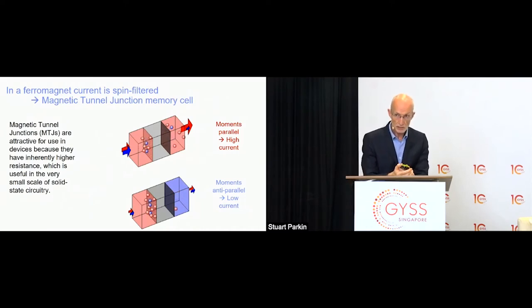Now, when you extract current from the surface of a ferromagnet into an insulator, it turns out, because the material is magnetic, this means there are more electrons with their spins oriented in one direction than the opposing direction. This means automatically the current is spin polarized. Moreover, by choosing that insulating layer properly, the insulating layer itself, even though it's non-magnetic, can further spin filter the current, so that the current, which is tunneling across the insulating barrier from one layer to the next, can be up to more than 90% spin polarized. In other words, the electrical current consists 90% of electrons of majority spin polarization.